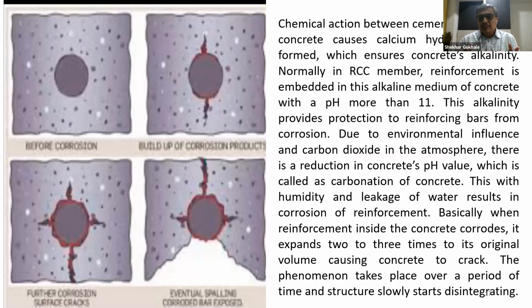And as long as the reinforcement bar is within that dense or properly compacted concrete, the reinforcement will not have any corrosion. But because of the environmental influence and carbon dioxide in the atmosphere, there is a reduction in the concrete's pH value. This pH value starts reducing from 11 to say 9.5 or so.